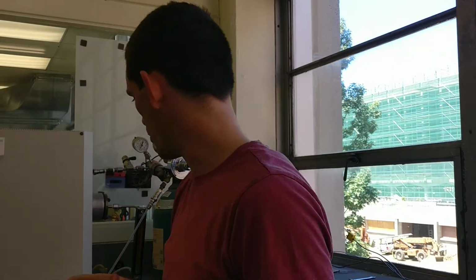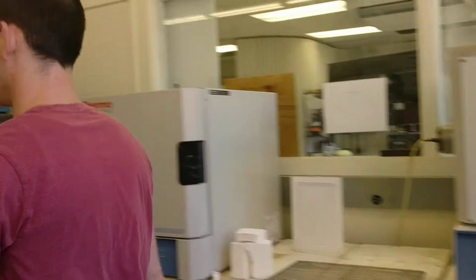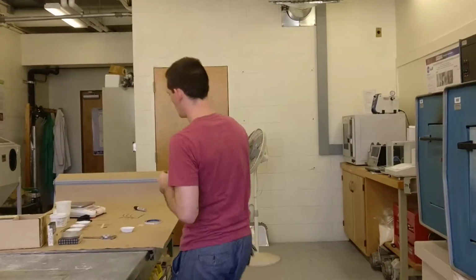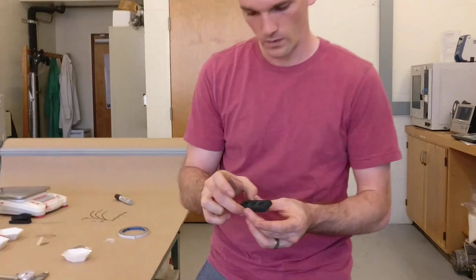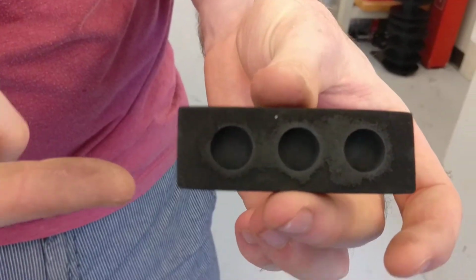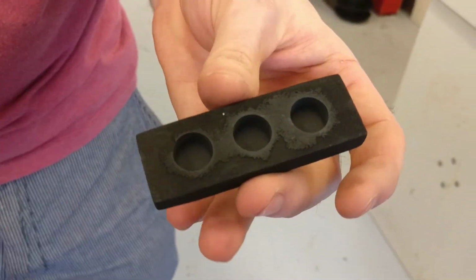If oxygen interacts with this carbon at temperatures above 600 degrees Celsius or so, the carbon will start to turn into CO2, and degrade the molds. That's what we don't want. And you'll actually see these old molds have been affected by that through some experimentation. You see like the surface of them is not very good, and the carbon will come off very easy from them. So you may have to make some new ones of those.